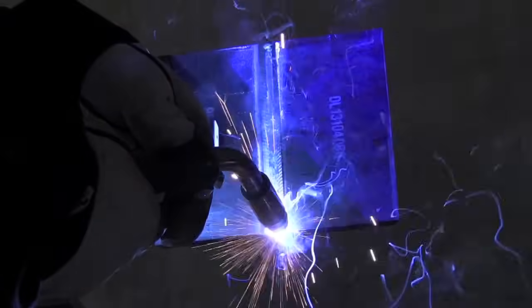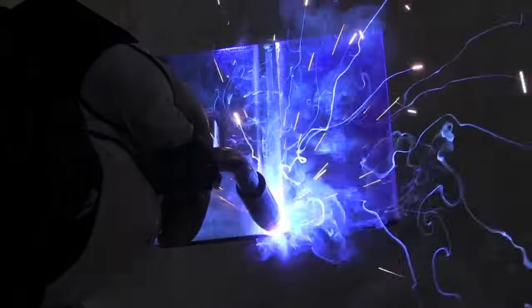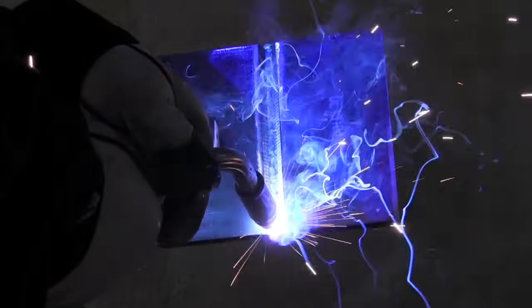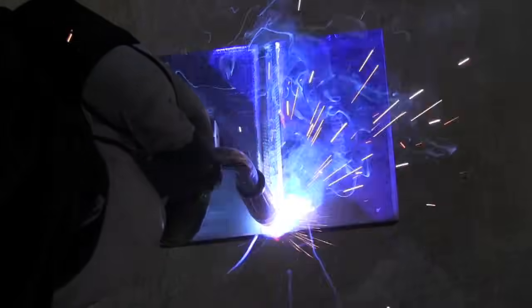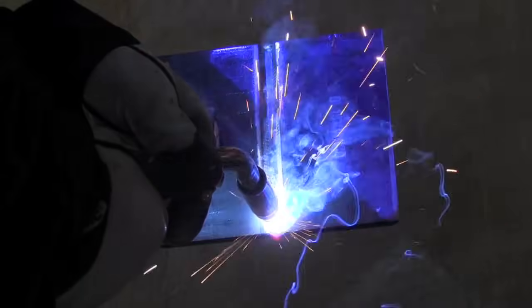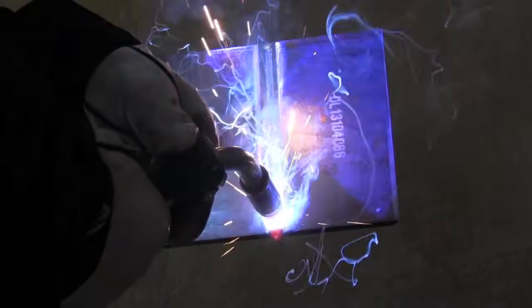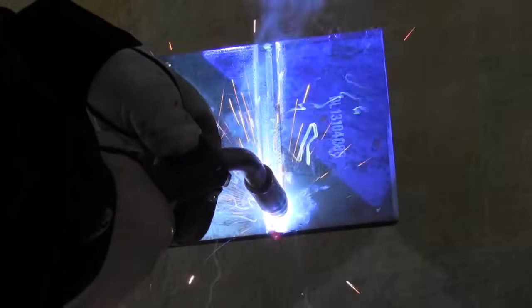Now we're going uphill. And really my experience has been, you don't really have to let it cool off a whole lot between the root pass and the second pass. In fact, I have done it where I didn't even stop. I just made a U-turn and kept going. And especially if I'm just marginally, a little bit cold, it really works out really well that way.